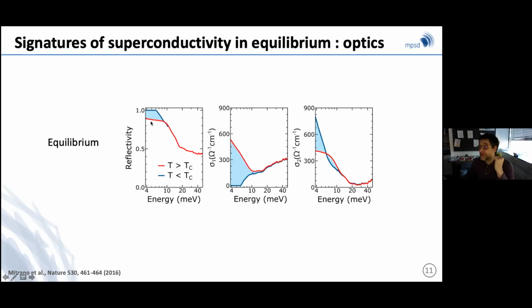The first thing that happens is that the reflection coefficient becomes exactly 1 for all frequencies up to an energy scale, which is the superconducting gap. The real part of the optical conductivity is 0 for all frequencies below the gap, except at 0 frequency, which is not shown here, where I have a delta function in sigma 1. And this delta function is reflected in the imaginary part of the conductivity, which diverges like 1/omega toward low frequency. So the presence of a pole in the real part of the conductivity is reflected by a divergence toward low frequencies of the Kramers-Kronig transform of sigma 1.